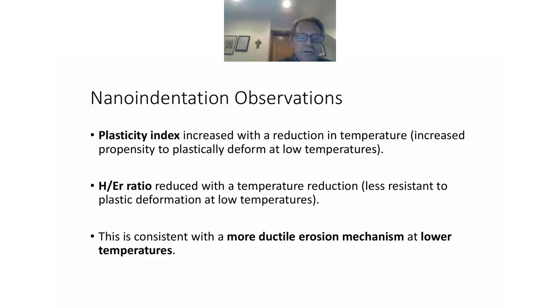So it's telling us that the system is allowing more plasticity and more flowing of chains over each other at low temperature. And similarly, the H over E ratio reduces with reduced temperature, so it's less resistant to plastic deformation at low temperatures, and it's consistent with a more ductile mechanism of erosion at low temperatures. We'd like to take it slightly lower in temperature just to confirm we do actually get into a brittle regime, which is what you would probably expect. But it's good news if you're going down to -30, then it doesn't appear you get brittle behavior of your coating.